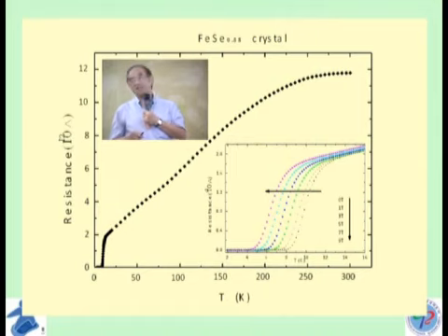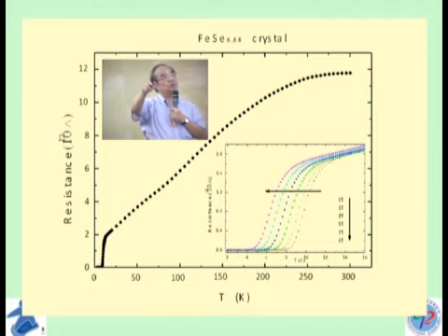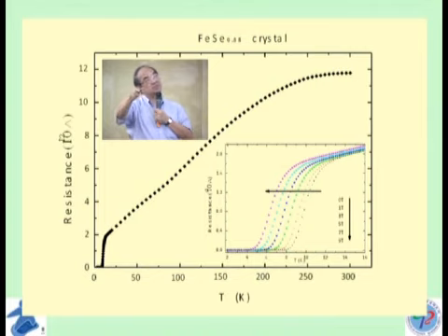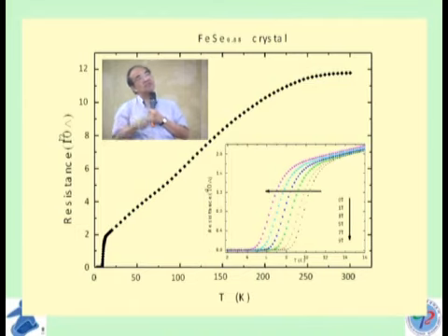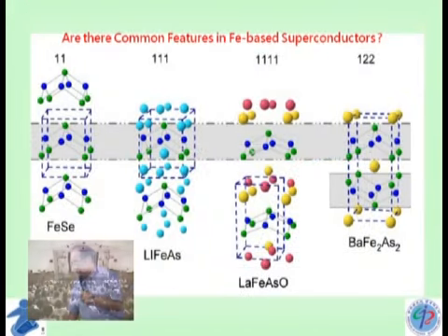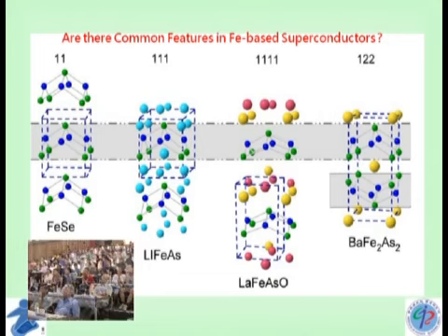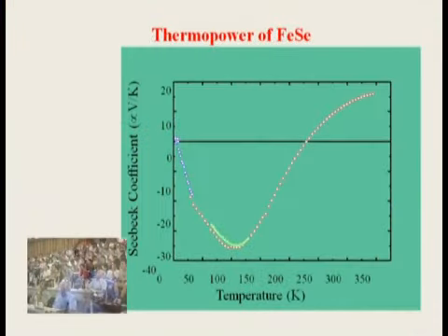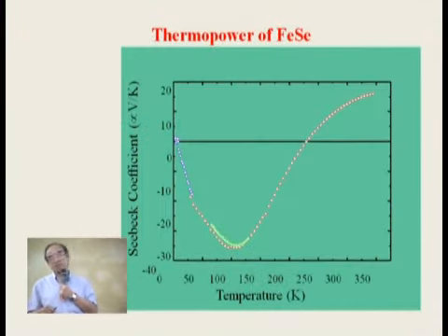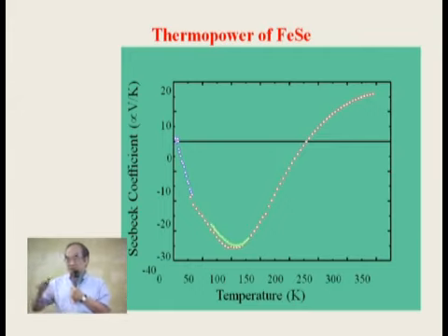One here. This is not like a normal metal. A normal metal has an almost linear dependence, and then drops. But here you see a sort of bump, and there's a dip, a small change here. So you see something already. Of course, we asked ourselves, what are those features? Definitely this is coming from that layer here. So we measured again using another method, the so-called thermopower, the thermoelectric effect, which is also a technique to reveal the electron transport in the system.